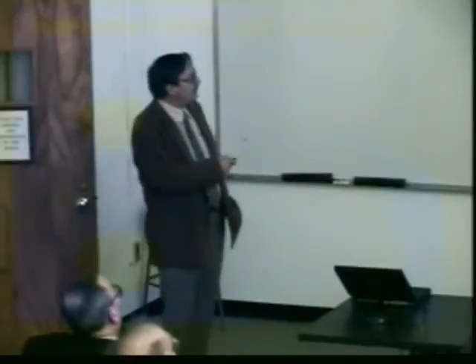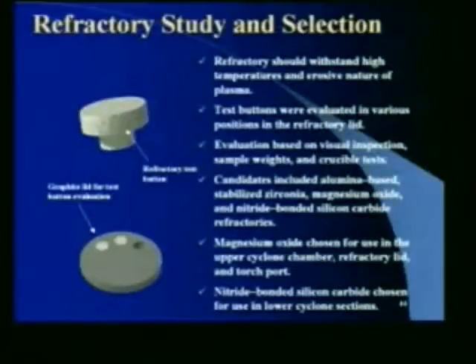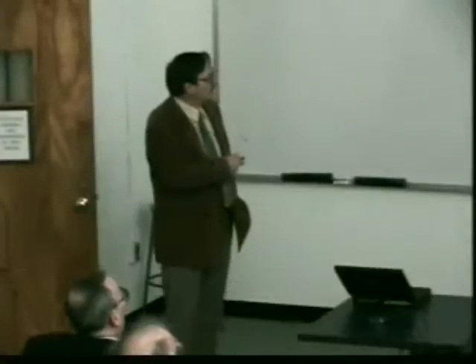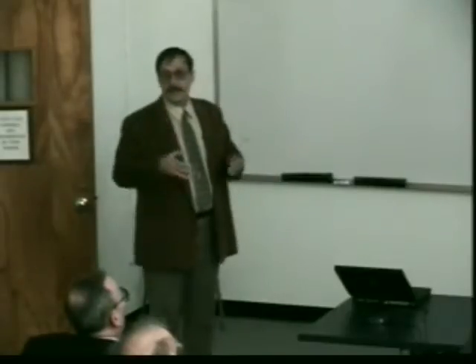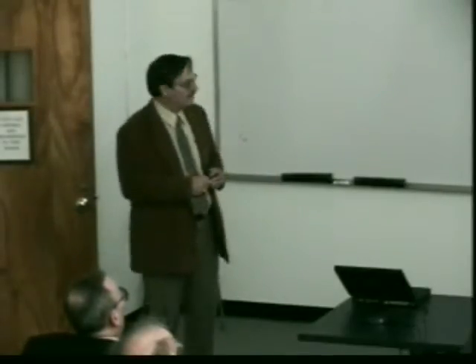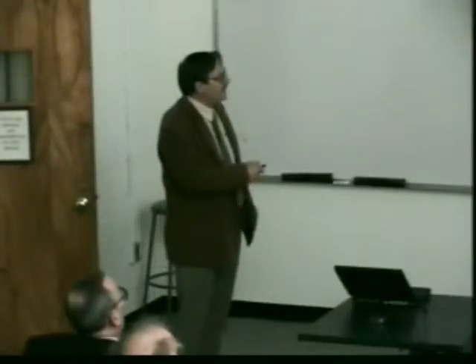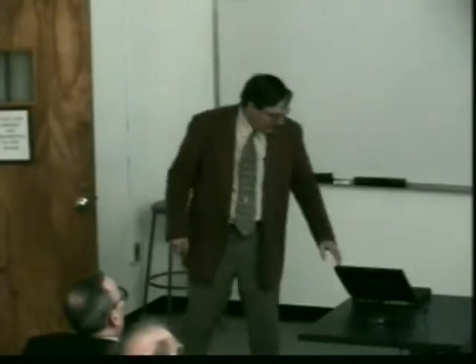Refractory selection. To study refractories, we took the lid of this reactor and machined holes in it where we could put various materials into the top, and then we looked at what happened to this exposed lower surface. We looked at a bunch of different materials: stabilized zirconia, alumina, magnesia, nitride-bonded silicon carbide, and so on. It's really a series of experiments with buttons in the top. The reason we did this is that it's very expensive to reline this reactor with different refractories, as you might imagine. But we came up with the fact that magnesium oxide is best in the upper chamber, and nitride-bonded silicon carbide is better in the lower chamber.